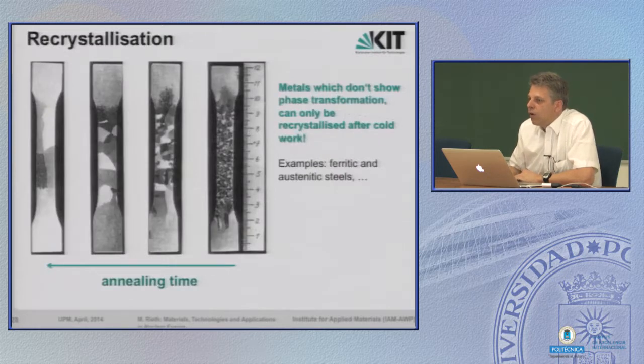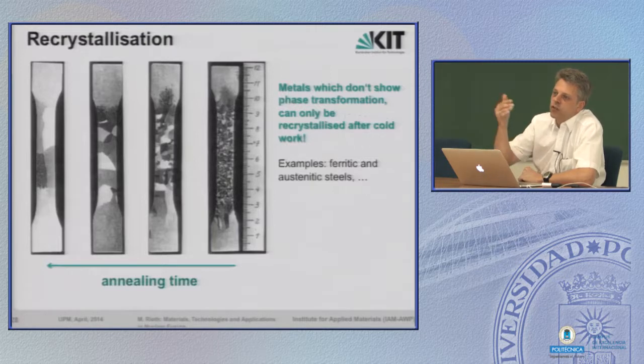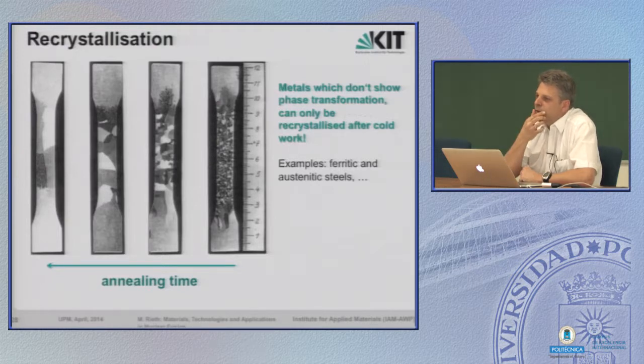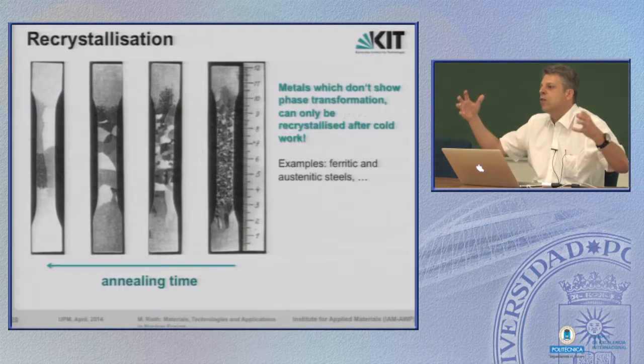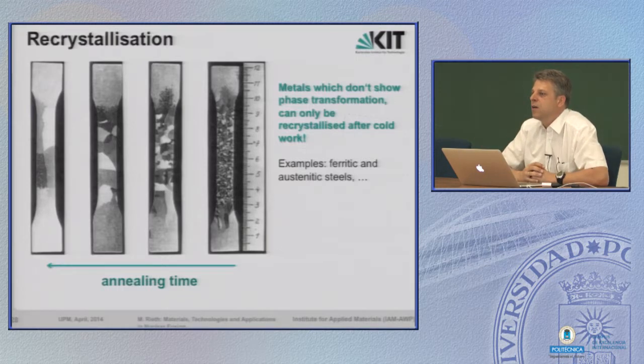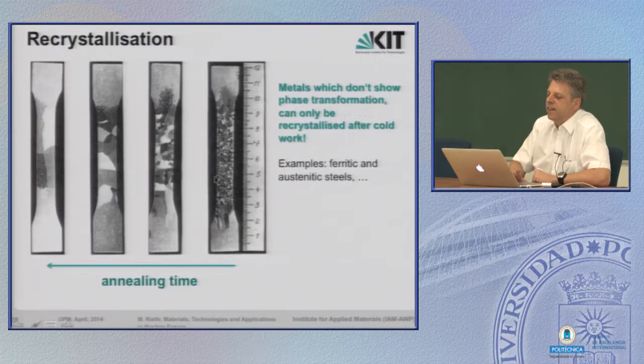What happens with austenitic steels or ferritic steels? Steels which don't show this transformation from FCC to BCC and vice versa. If you want to change their microstructure, then you can do only one thing. You can heat them up. What happens? The grains grow by a certain amount, and that's it. But we are most often not interested in coarse grains, we are most often interested in fine grains due to the hardening effect. And the only thing you can do with such materials is you have to cold form them, you really have to hammer them or roll them, forge them, whatever.